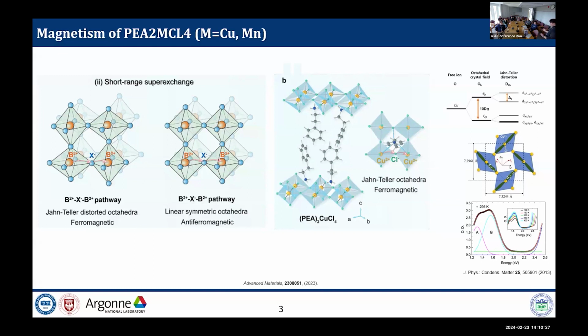Also, the Jahn-Teller distortion can cause some transition in the d orbital, because this is the hole state and this is the fully filled electron state. So an electron can transition from here to here. This is called a d-d transition from the Jahn-Teller distortion. Also, it makes some abnormal absorption under the band gap.